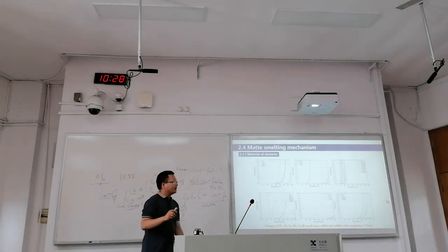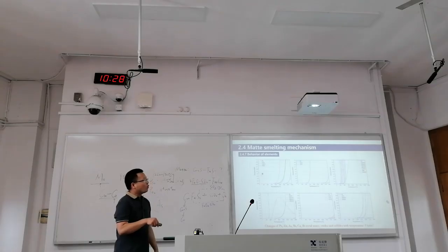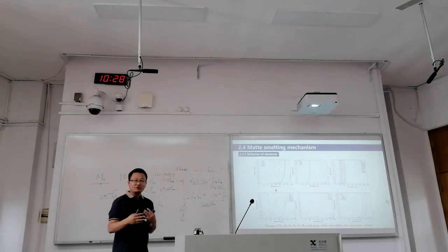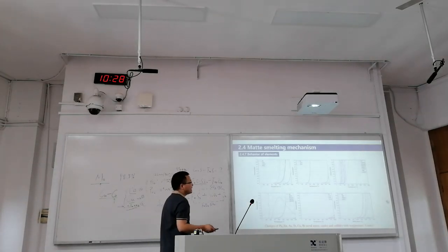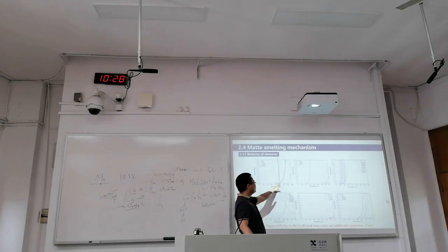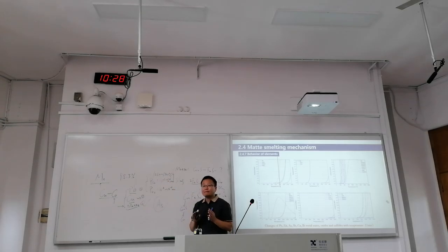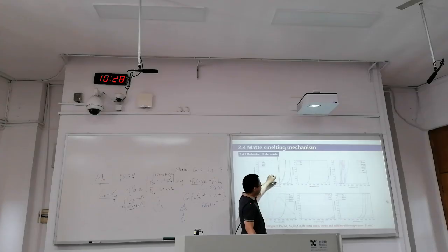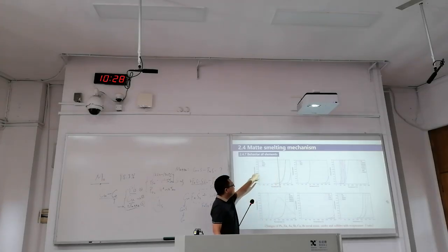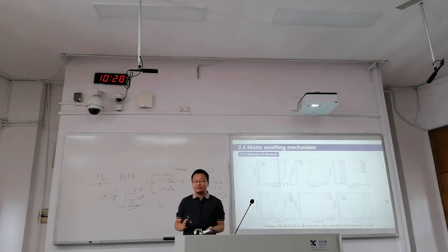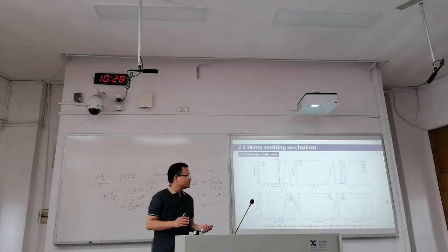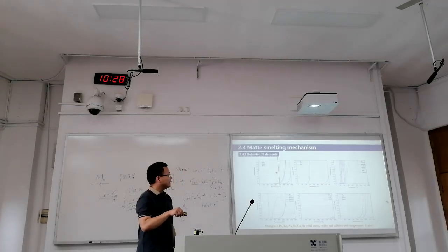And if we are reading this figure, the y-axis is pressure, and the x-axis is temperature, the processing temperature. So if we are putting the first line, 1250, this is what we have been instructing, the temperature for copper making. If we are having such a temperature, and we are reading that, there will be some partial pressure for lead sulfide. Which means when we are having partial pressures of some species, some compounds, it will move to the gas phase.